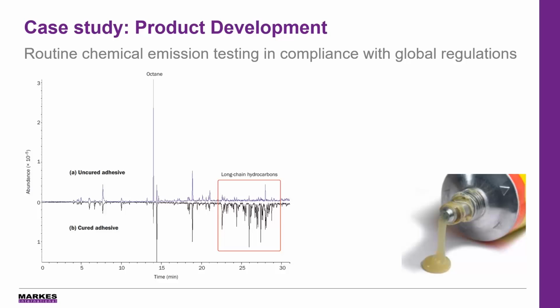And it's clear from the data that that curing process causes a reduction in the level of octane, but an increase in the emissions of those long chain hydrocarbons. And really it's this ability to compare samples before and after processing that allows manufacturers to optimize that curing process and to minimize the chemical emissions from the end product.